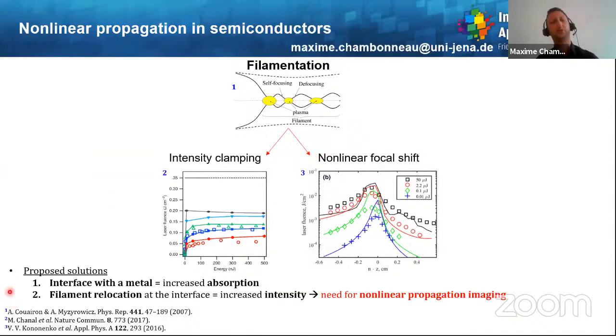So here are the solutions we propose. Well, first, in the frame of semiconductor to metal laser welding, we will use an interface with a metal, not only pure silicon, meaning that the absorption should be drastically increased. And moreover, we propose a filament relocation at the interface, meaning that theoretically the laser intensity should be increased. But to do so, we need nonlinear propagation imaging.